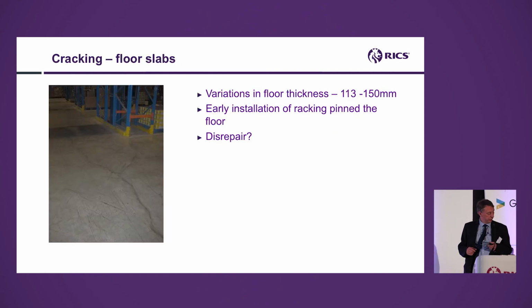And then almost finally, another warehouse in Belgium where we had some quite profound cracking in the floor. And this was sufficient to cause great alarm and despondency, and the tenant started to withhold rent. Now, again, we're talking Belgium, and this is not a UK issue, but the principles are the same. So why have we got all this cracking? And they put resin in and tried to repair it. The big problem was that as they put their materials handling equipment over it, that shook around a bit. They lost a pallet. There was concern over deterioration and so on and so forth.